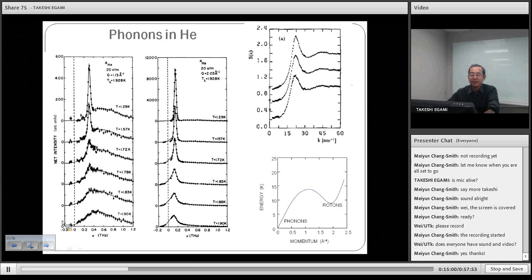And this data shows the intensity profile at each particular Q. This is a Q at 1.13, so it's around here. It shows how the peak shape changes with temperature. So in regular normal fluid, this peak is very broad, right? But it becomes sharp when the helium goes into the superfluid state. In the same way, this peak, which corresponds to the roton, that's the roton frequency, is a little bit sharper than this peak, but it becomes really sharp at low temperatures when the system goes into a superfluid state.